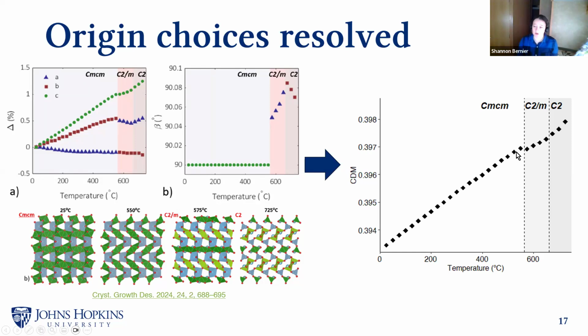So we have an indicator that a phase transition is occurring. And as Davor mentioned, these are all experimental points. If we had a denser series of points up here, we might even be able to see a better discontinuous transition at the higher temperature phase transition as well. This also takes into account both the A and the B plot at the same time. So this is kind of just a nice example of how the CDM can simplify discussions that would otherwise be a little bit complicated.